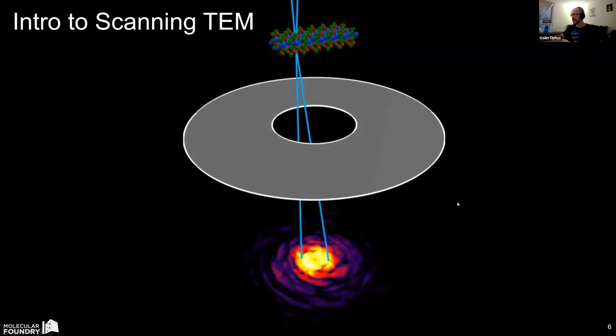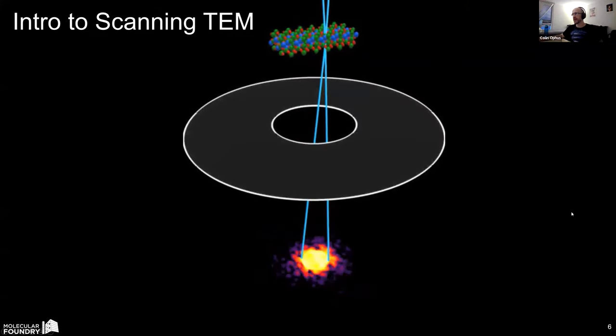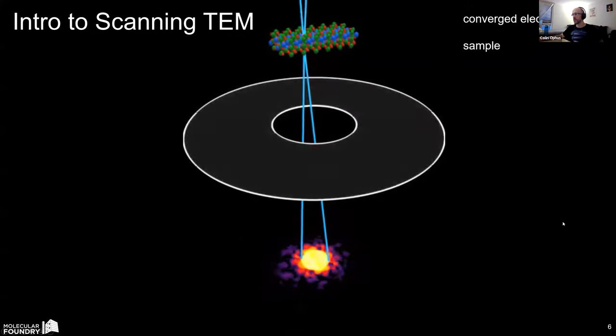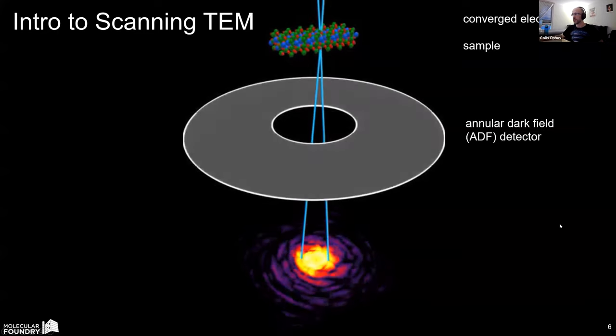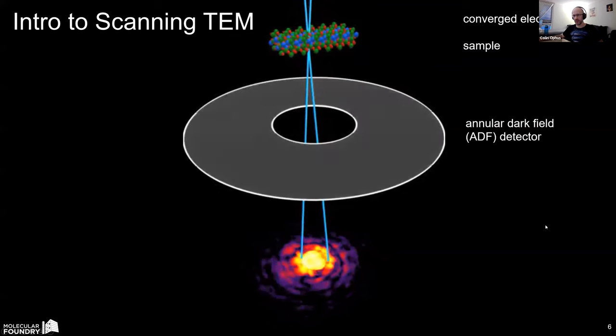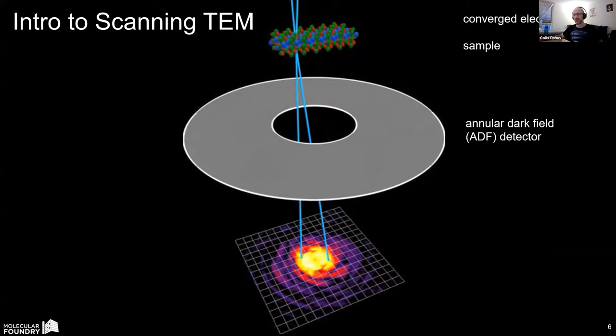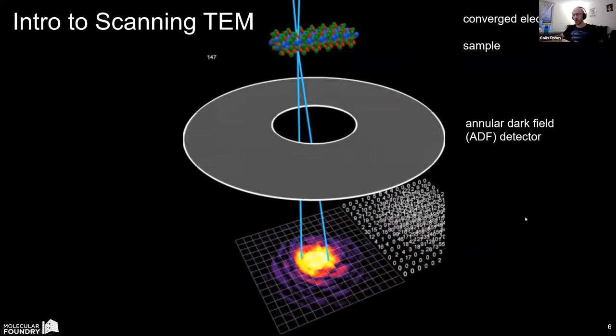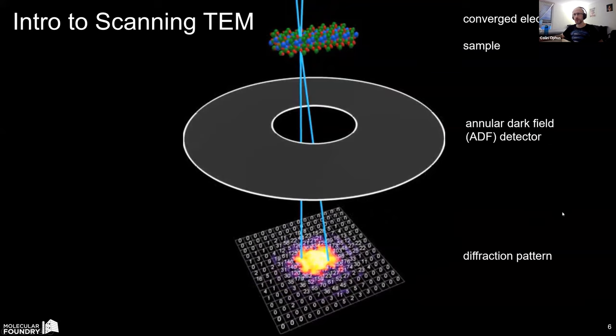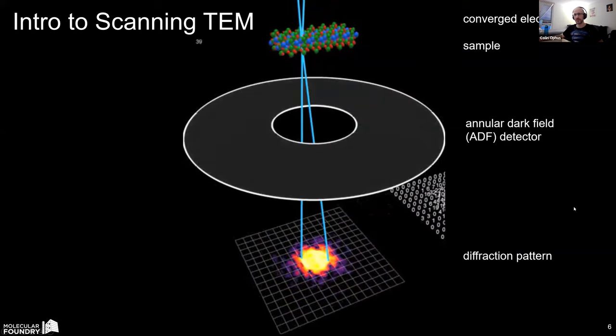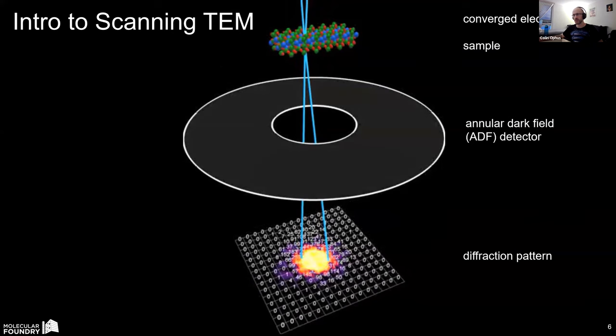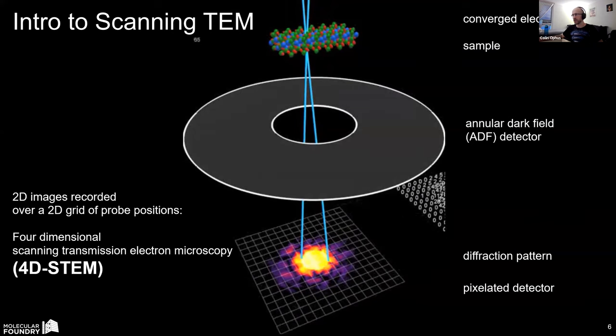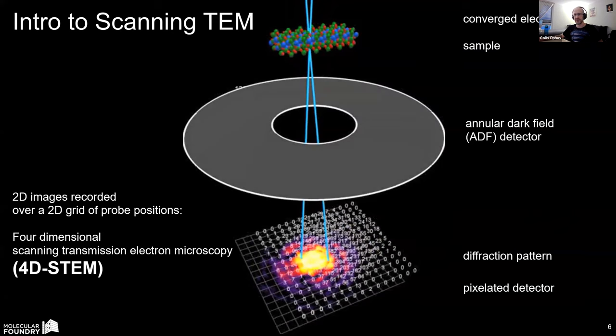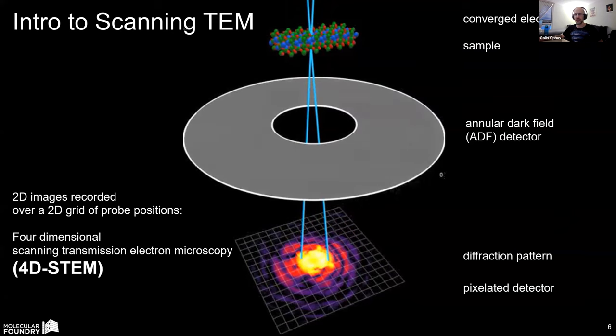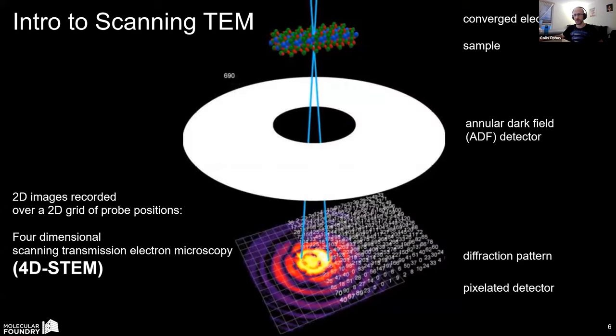So the technique that I want to talk about, though, is 4D STEM. So conventional imaging using a converged electron probe passing through the sample used a giant monolithic single pixel detector. And then we would move the probe to the next position, collect electrons, move the probe to the next position, et cetera. But these days, our detectors are so fast, we can use a pixelated camera, record a full two-dimensional image of the diffraction pattern at every probe position, step to the next probe position, et cetera. So the result is a two-dimensional grid of probe positions, and at every probe position, a two-dimensional image, giving the name of this technique 4D STEM because of the 4D data.